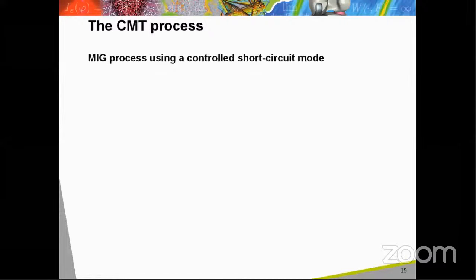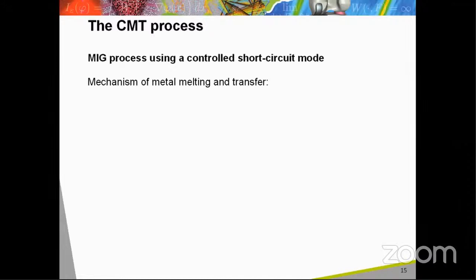This process is considered as a MIG process using a controlled short circuit mode. With this process, droplets of liquid metal are deposited according to a regular cycle comprising 4 main steps. The filler wire is fed or retracted according to the step in the deposit cycle.